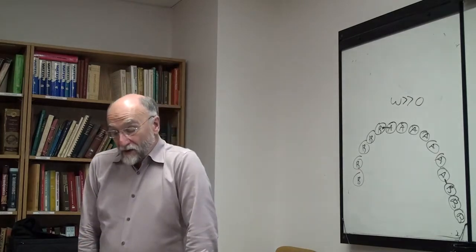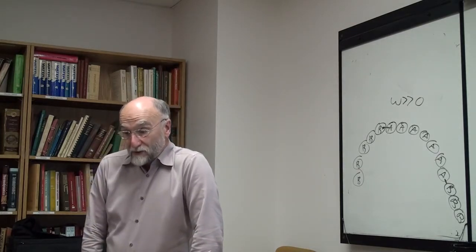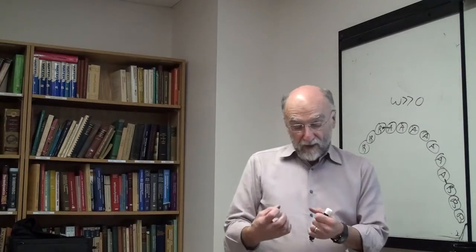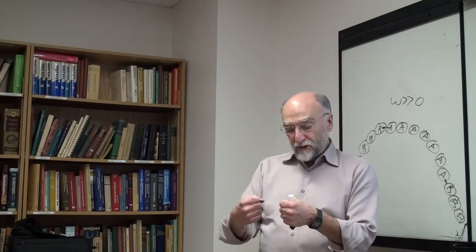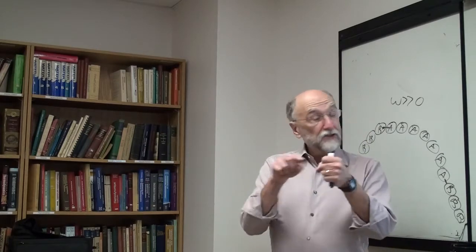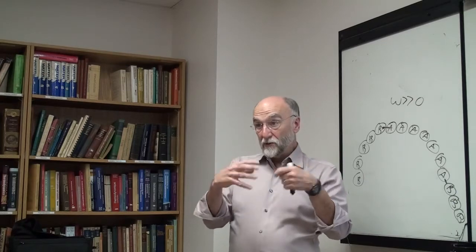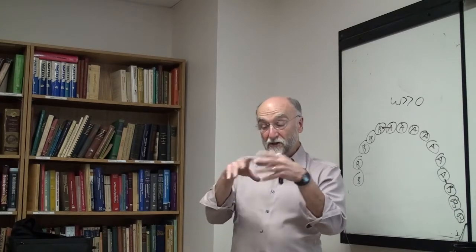Apparently, I've heard the Onsager thing has been worked out. It gives you a miscibility gap. Also, they have done this sort of thing using molecular dynamics, where you actually simulate a liquid in 3 dimensions, and the only energies are the pair energies. Okay, and then you set Z greater than 2. You have only the pair energies, and you see, will the thing separate into 2 phases, and it does.